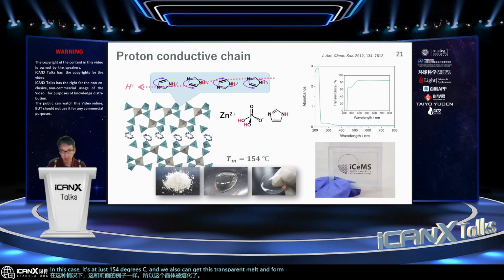When we consider the possibility of switching proton conductivity by light, the very important point is how transparent this glass is. And obviously this glass shows very high transparency, almost equivalent to the silica glass in a daily-use window. We can also fabricate a very thin film without any color and with transparency. But please remember, this glass has a very high proton conductivity inside.